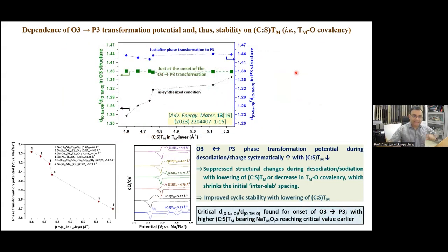When we estimated the ratio between the interslab spacing and the transition metal slab spacing, we found that for the onset of the O3 to P3 transition there is a kind of fixed or critical ratio. So we found a critical ratio for the onset of the O3-P3 transition during charging or electrochemical desodiation. For the materials having lower charge to size ratio, the starting interslab spacing to slab thickness ratio is much, much lower, way below this critical ratio. So a lot of sodium extraction needs to be done before this ratio hits the critical ratio and leads to the onset of the O3-P3 transition. A lot more sodium can be extracted before this transformation gets initiated, and hence the subsequent transformations do not take place if we don't go to too high an upper cutoff potential.